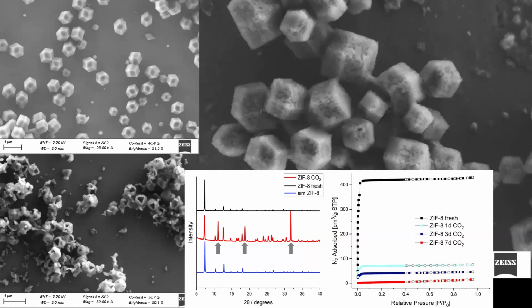If you leave it there, eventually it will degrade. Of course, if you put it in water and you don't remove the CO2, or you put it in an incubator with cells where you have 5% of CO2, because cells have to be cultured with 5% CO2, it's a matter of minutes or hours that you destroy the MOF. And I want to put this in a paper because it's very interesting.